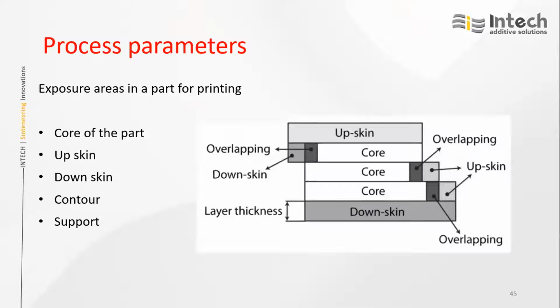For a given component, there will be exposure areas like core of the component, upskin, downskin, contour, and support. The key process parameters are only 4, that is power, speed, hatch spacing, and layer thickness.